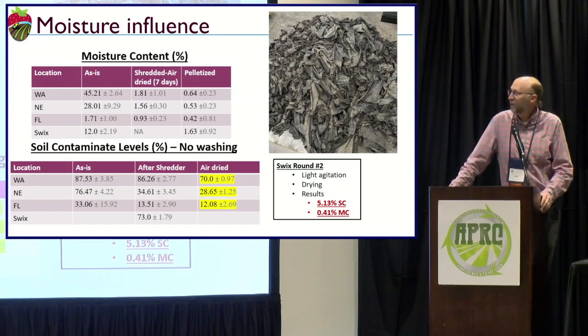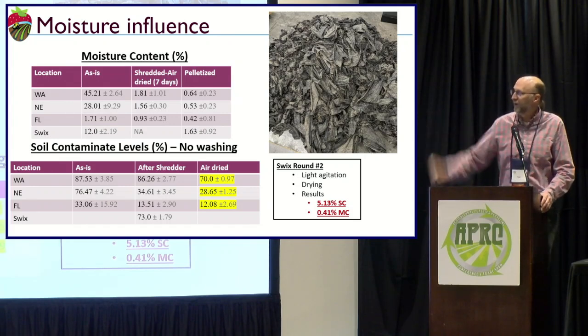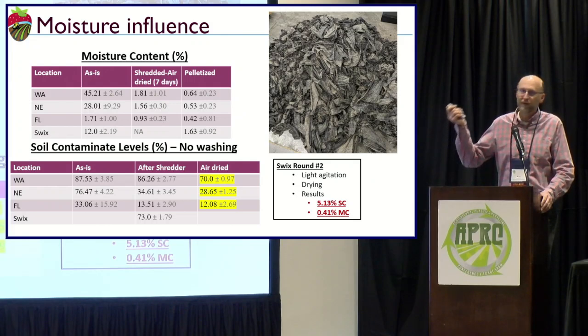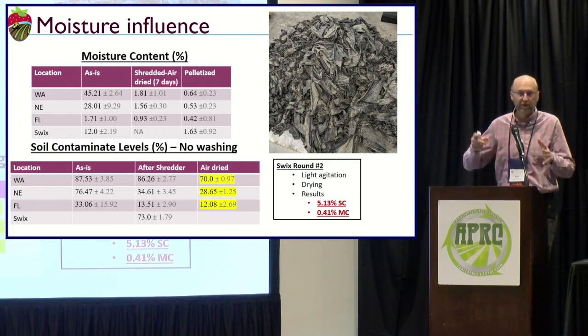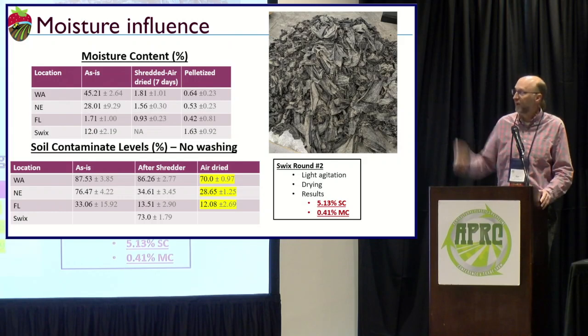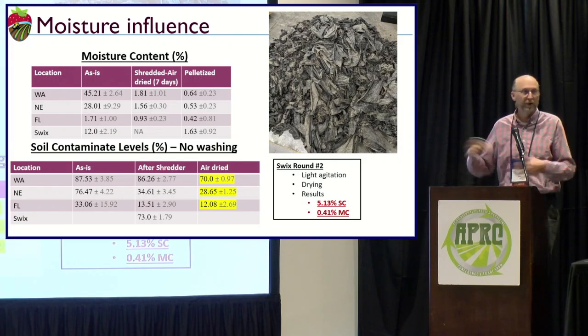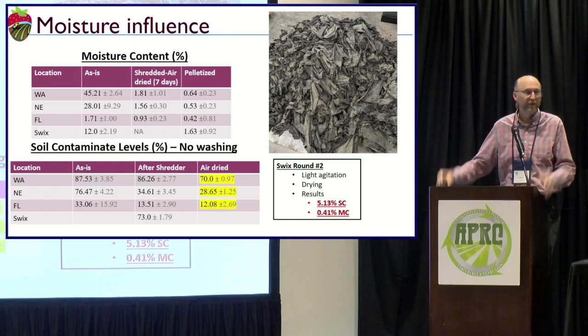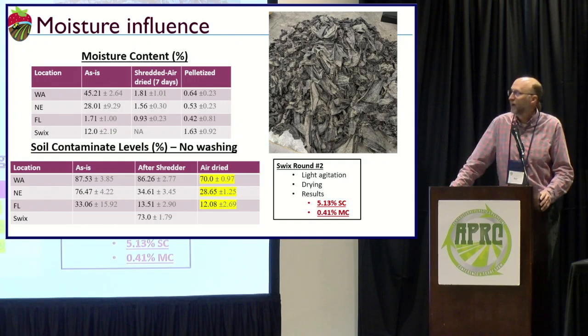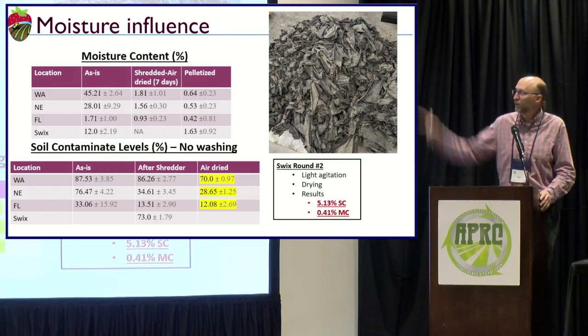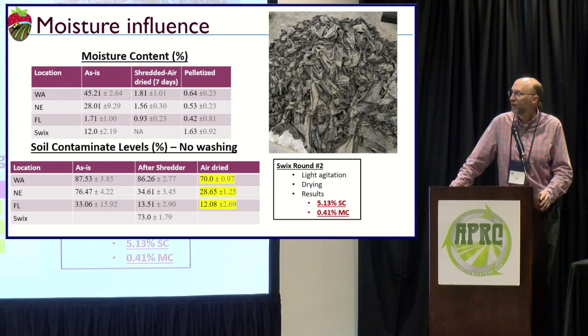So that's your moisture content there. We measured the moisture content as is, when we first got it in, and then again after we shred it, because we shred it down and lay it out on the floor to dry a little bit. And then we pelletize it. She took a look at the moisture contents throughout all those operations, and you can see that after you just air dry it for a little bit, you get a pretty high reduction in your moisture content.